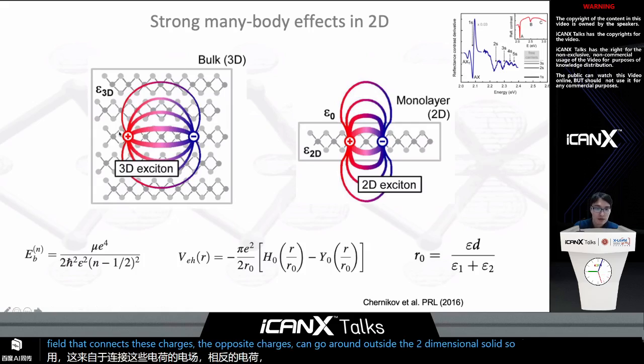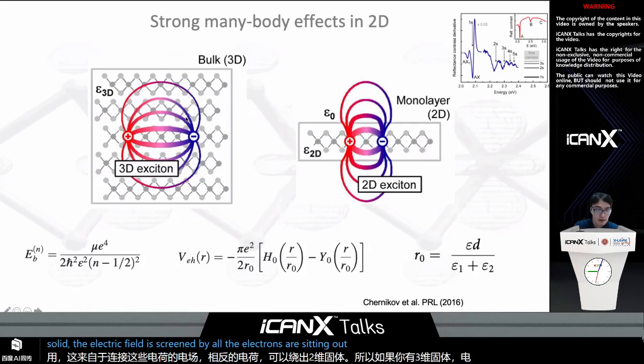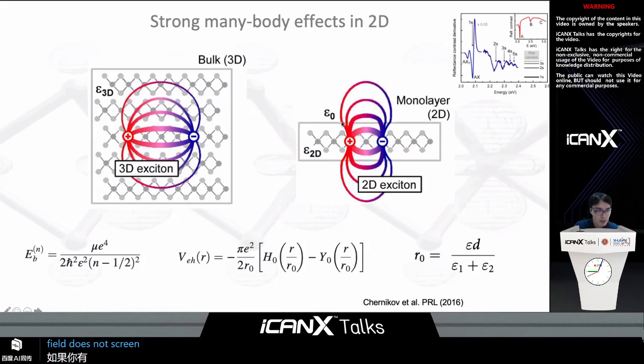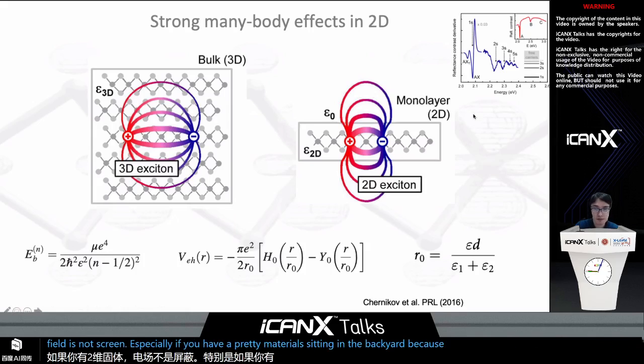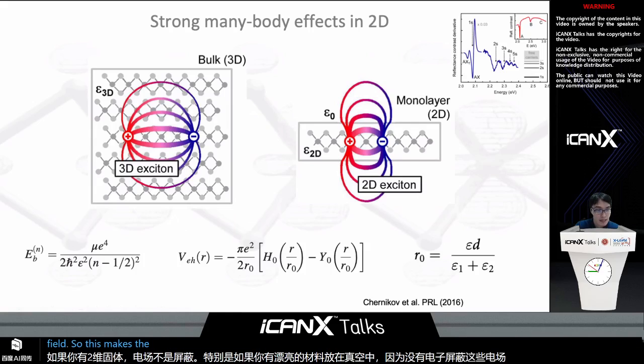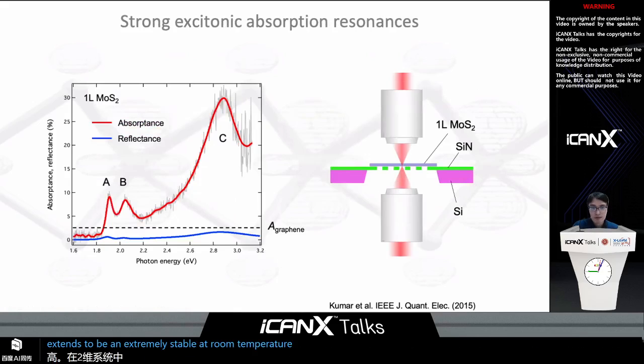So if you have a three-dimensional solid, the electric field is screened by all the electrons that are sitting outside the plane. But if you have a two-dimensional solid, the electric field is not screened, especially if you have a 2D material sitting in vacuum, because there are no electrons to screen this electric field. So this makes the binding energy of the exciton extremely high in two-dimensional systems, and excitons extremely stable at room temperature.